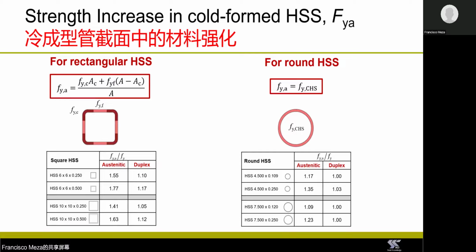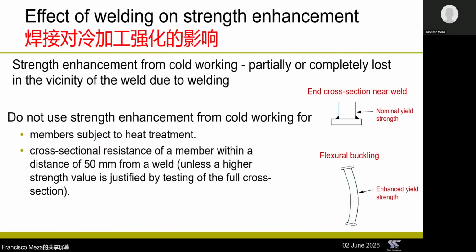So Eurocode 3-1-4 allows you to calculate an average yield strength for the entire cross-section based on the yield strength that is developed in the corner regions and also in the flat regions. Now, one important thing to take into account is that you cannot use the average yield strength when designing a cross-section that contains a weld or that is adjacent to a weld. And this is because of the annealing effect of the weld, which can completely remove the increase in strength due to cold work. So if the cross-section is near a weld, you will have to use the nominal yield strength when designing the cross-section.